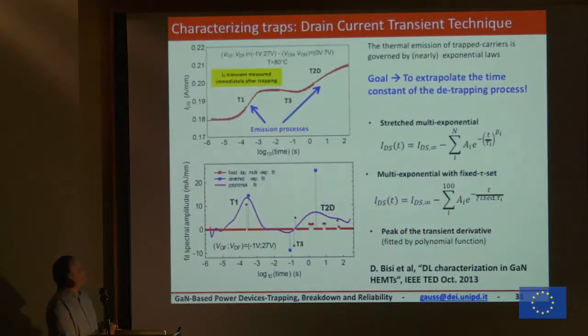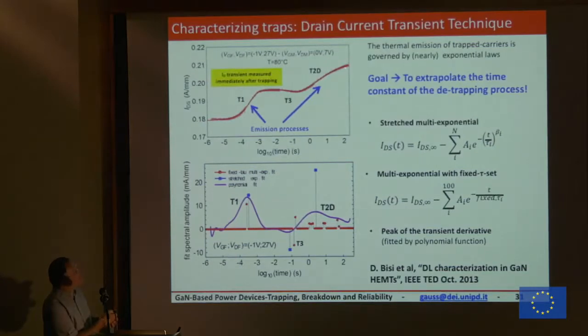Let me go back to here, and you see a real measurement. So this is, be careful, this is a logarithmic scale. So we are going from microseconds to hundreds of seconds. So this is 8 orders of magnitude span. And we see the current evolution. We start with the current at a certain level, then we have 1 transient and 2 transient. So in the double pulse measurement, you just measure your current here, or let's say at one of these points. Here we are having all the current evolution. And with the current evolution, we see this transient.